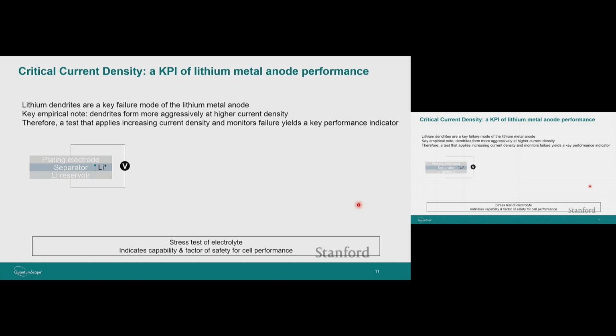So lithium dendrites, as I mentioned, are a key failure mode in lithium metal anodes. And a key empirical finding over several decades is that dendrites form more aggressively at higher current density, meaning higher charge rates. As you pass more lithium per area, the lithium dendrites form more and more aggressively. And it's been a big mystery in the field as to why that is. We think we've understood why that is.